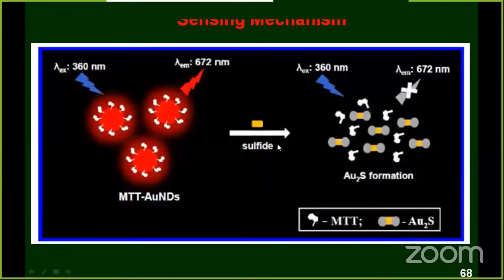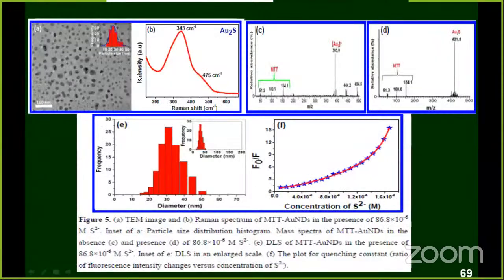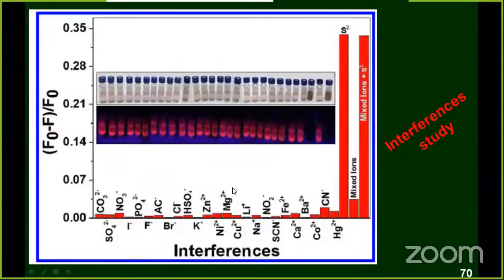Again, Au2S is produced here, and we took the Raman spectrum. This is the confirmation spectrum of Au2S, and the particle size increases. This is also because of Au2S, and we took the mass spectrum, which confirms Au2S. Then there is the Stern-Volmer equation, and these are the diameters. This one is the dynamic light scattering values. So using all these things, we have predicted the mechanism.